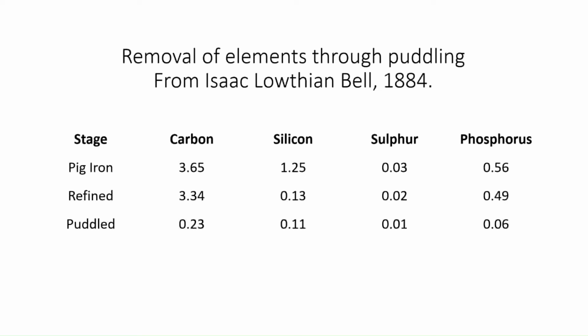Just to demonstrate how this worked in the two-stage process, these figures are from Isaac Lowthian Bell, who produced a very important book in the 1880s. And he was one of the first thermochemists dealing with the iron industry in Britain. So this shows how you reduce the carbon and the silicon and the sulfur and the phosphorus when you turned it from the pig iron into the refined iron by using the running out fire, the refining surface, and then how puddling it took that whole thing a stage further. I'm just looking at the time to make sure I don't overrun. It just demonstrates how the whole thing worked.